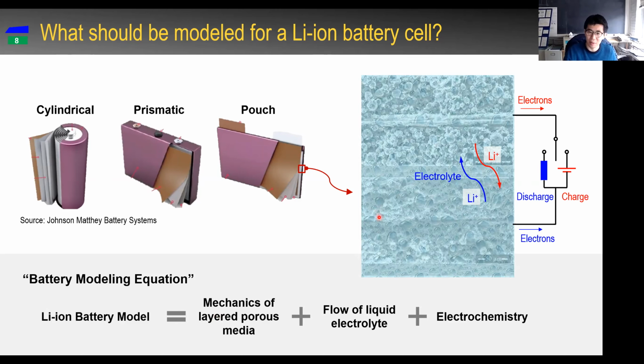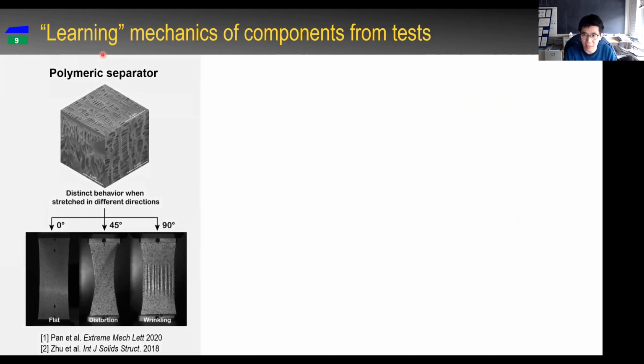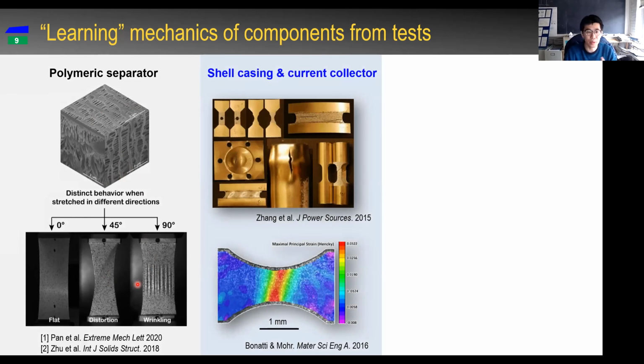To really develop a good model for this solid skeleton, we have to test a lot. We have to test all the components. There is a fancy word called learning. So we have to learn mechanics from component-level tests. Our team has been working on this for, let's say, 10 years, and has almost tested everything, like the polymer separator. We did reconstruction of the polymer, and we did tensile tests on the separator. We also tested, for example, the shell casing, the enclosure of the battery. And we also tested the current collector, which is the metal, the aluminum and copper foils.